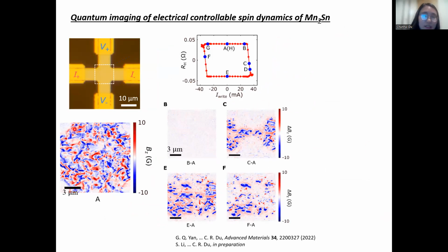Then we will study the current dependence of the NV imaging. So we focus on the cross area of the Hall bar device. At zero current, we get a magnetic image, which is like this. Then we will monitor the current dependence of the magnetic state. Here, the zero current image was subtracted from the four images here to highlight the changes of the magnetic state. We can see that at point B, below the critical current, nothing changes. Then as we increase the current, the magnetic switching starts to happen. And if we further increase the current, it extends to the entire Hall bar device area. And if we reverse the current direction, the switching polarity also changes. So this is consistent with the mechanism of spin orbit torque based switching.